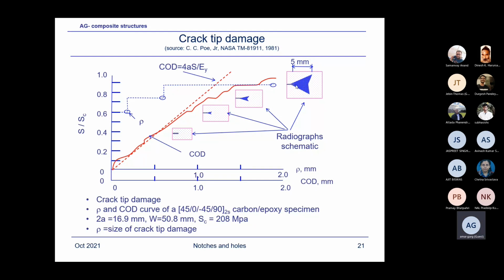So there's no way. The best way is to test the notched laminate and unnotched laminate, and using the equation predict the characteristic dimension. And that is the standard way we always do that. Rather than using the equation, some people might use the finite element method to predict that. But I found that rather than using the finite element method, with unnecessary complications, I would use these equations, which are simple and give the same result as finite element. I myself tested that.